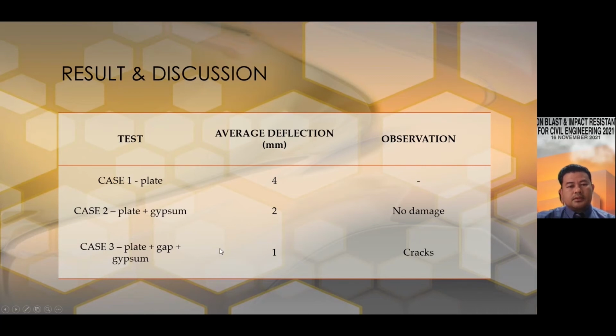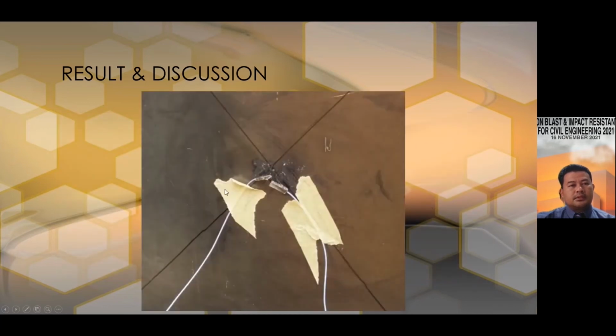The deflection of the plate was measured using a ruler. This is because the strain sensor we attached at the back was detached from the steel plate and does not give good results because of the high heat and the explosion, the blast wave. The glue cannot withstand it, and the strain sensor detached from the steel plate.